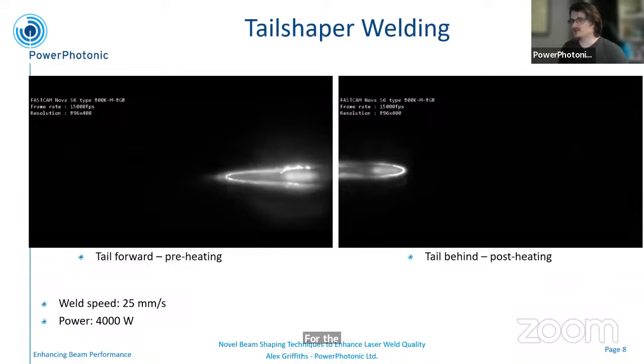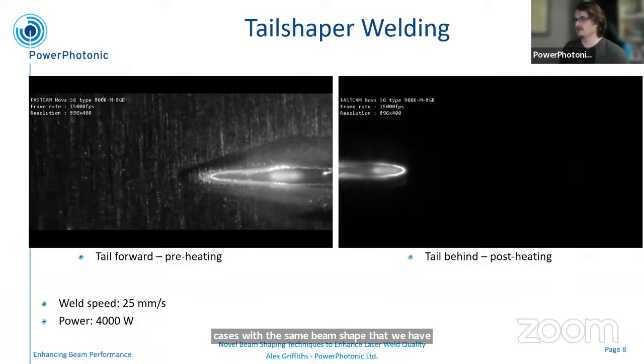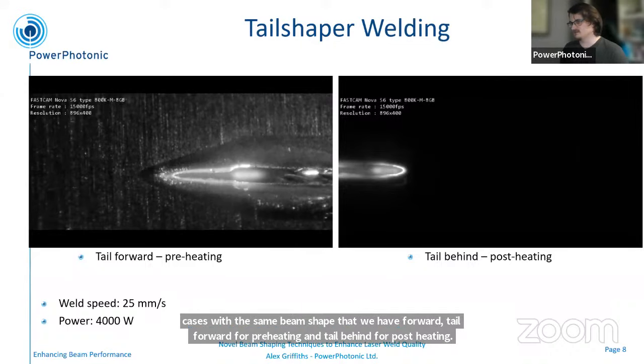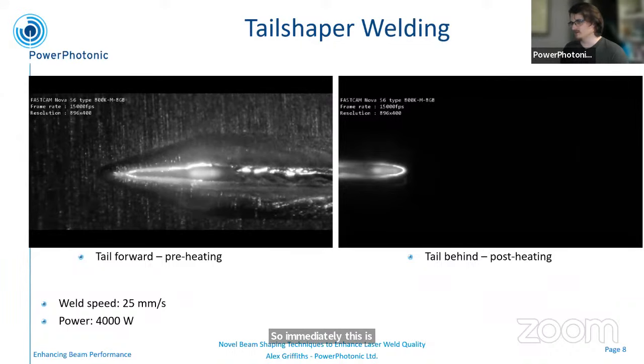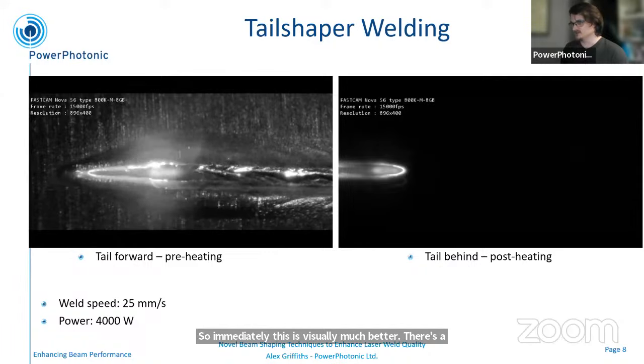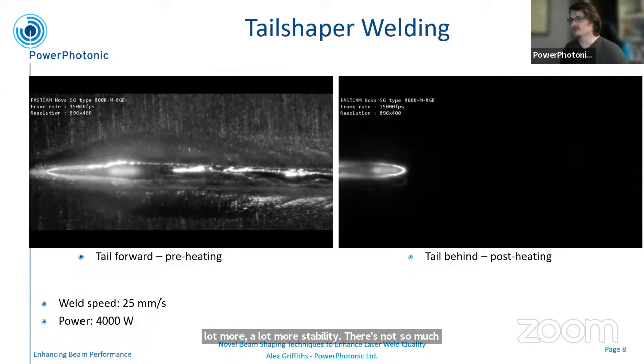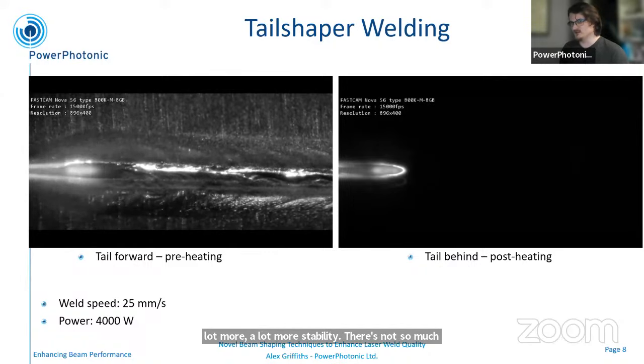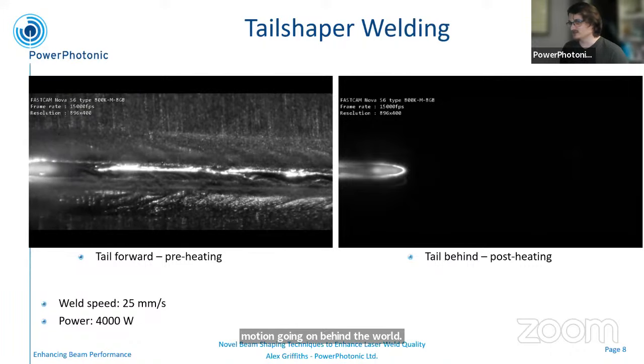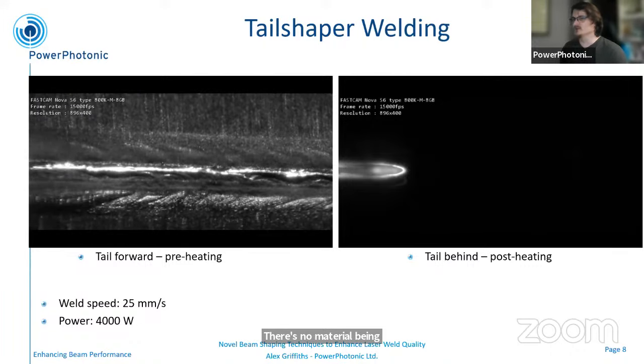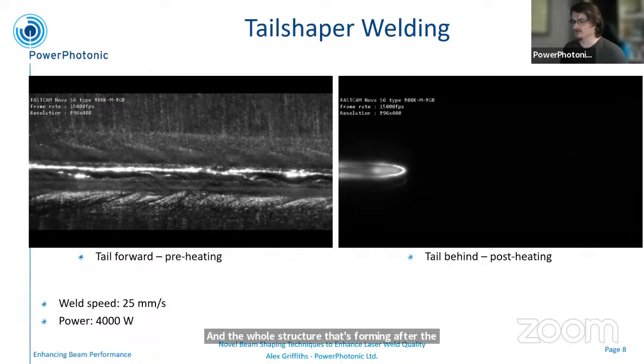Onto the tail shaper. Now we've got the two different cases with the same beam shaper. We have tail forward for preheating and tail behind for post-heating. So immediately this is visually much better. There's a lot more stability. There's not so much motion going on behind the weld. There's no material being ejected as far as I can see from the video. It's very smooth looking, and the whole structure that's forming after the weld is quite different.